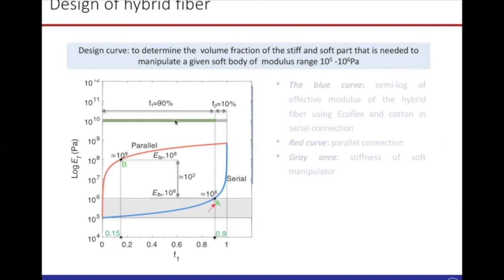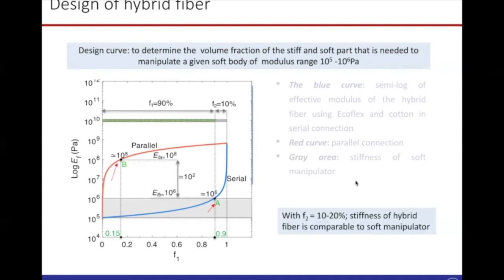Then we need to introduce a locking mechanism using gallium. Gallium could have some bending stiffness. So as we said in the beginning, we need a change in membrane stiffness and we don't need an increase in bending stiffness. A larger volume of soft part could lead to an increase in bending stiffness. So we want to minimize the soft part as much as possible, but without compromising the stretchability. So we believe a volume fraction of around 10 to 20% for the soft part should help to design a hybrid fiber with stretchability quite comparable to that of the soft body.